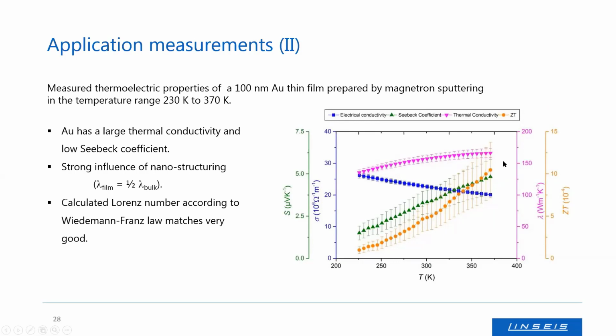For those who are familiar with the thermal conductivity of gold, the literature value for bulk material is approximately 300 watt per meter Kelvin. And for this thin film, we find only half of the value of the bulk material, approximately 150 watt per meter Kelvin. This shows that it's really necessary to measure the properties of the thin film and not to take just literature values from bulk material. This is not a measurement error, but real life.